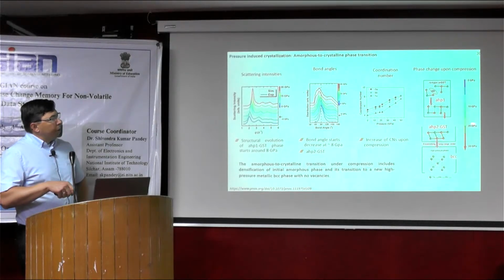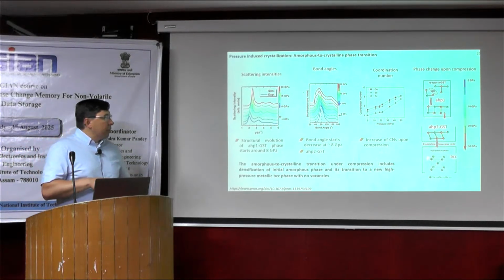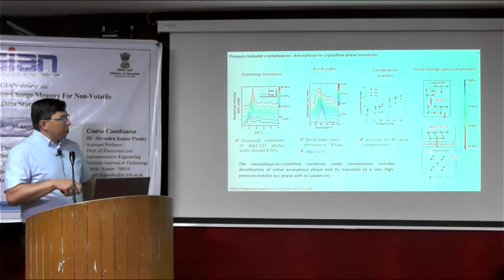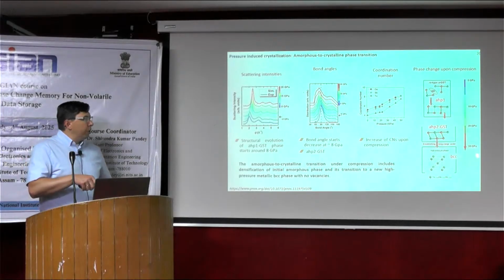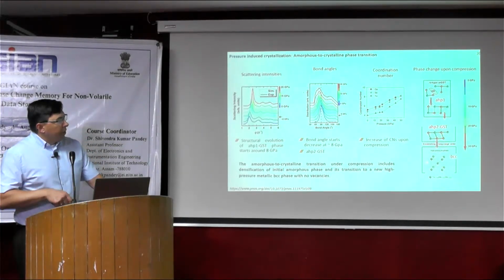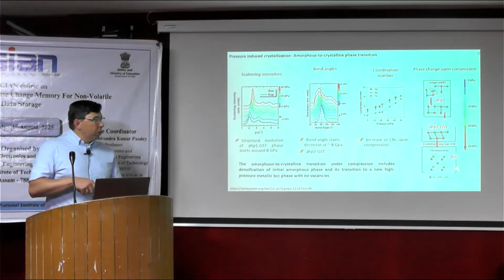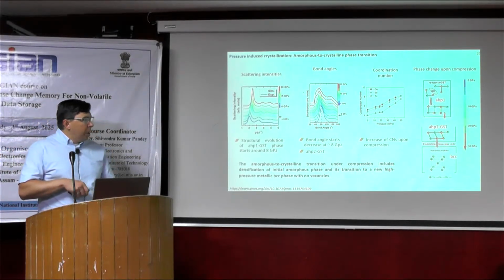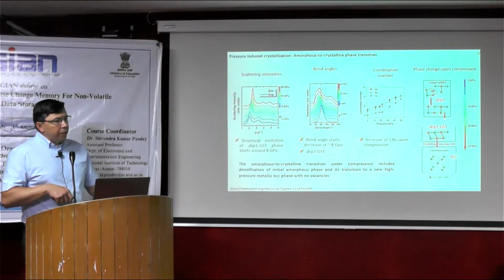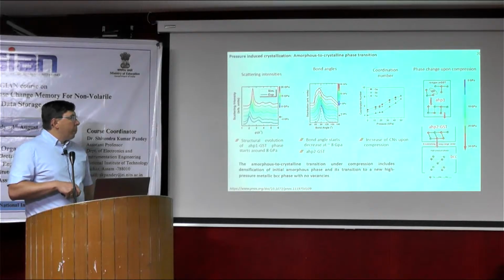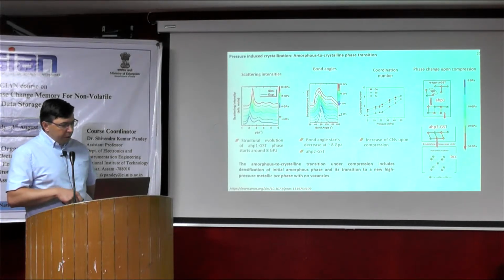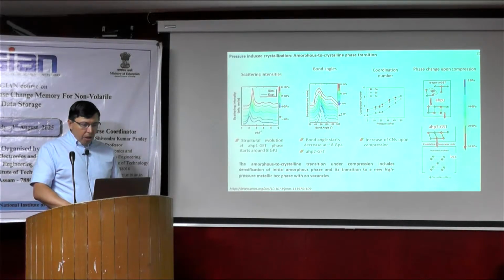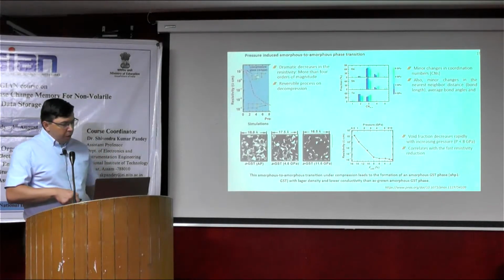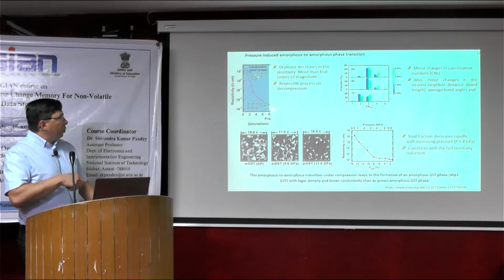And then on further densification, we go to the transition to the crystalline phase. It's around 30 gigapascal. It's also a cubic phase, but it's not an FCC structure. It's a BCC structure. This is also a highly disordered phase, and all elements like tellurium, germanium, antimony are located on each site, and there are no vacancies in this phase. So this transition is reversible from one phase to another phase.